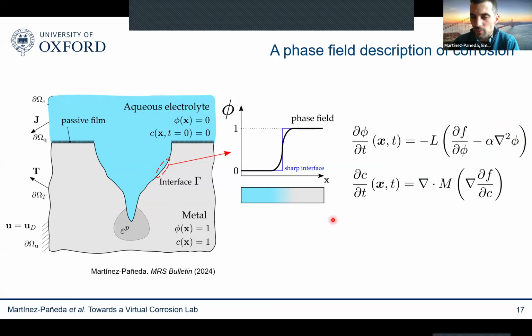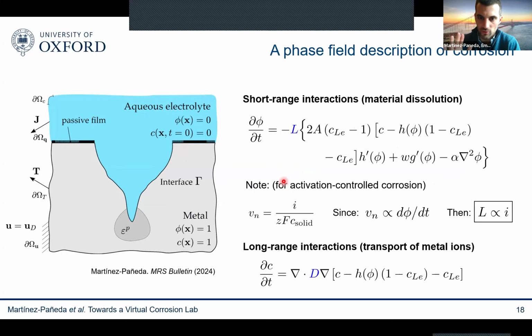And basically, in the simplest version, you have a system like this. So you have an Allen-Cahn type of equation, and then you have a Cahn-Hilliard type of equation without the gradient, basically. So an equation for the evolution of the phase field, and an equation for the evolution of the concentration of metal ions. Again, in the simplest form. And then you can make some constitutive choices. Most phase field corrosion models are based on the so-called KKS model. So you assume thermodynamic equilibrium between the solid and liquid phases. But basically what I want to say here is that you end up with two equations like this.